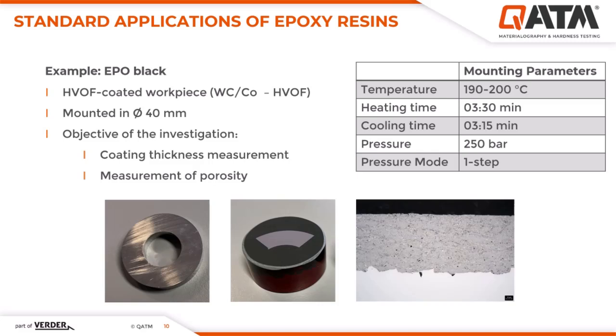Polishing with diamond particles was avoided as it could destroy the measurement of the porosity in the tungsten carbide cobalt layer. After the final grinding step with the Polaris M with 3 micrometer diamond grinding wheel, only oxide polish with Epoxyl F solution on a corresponding omega polishing cloth was used. The excellent sharp-edged preparation results achieved in this way allowed a perfect analysis of the coating.